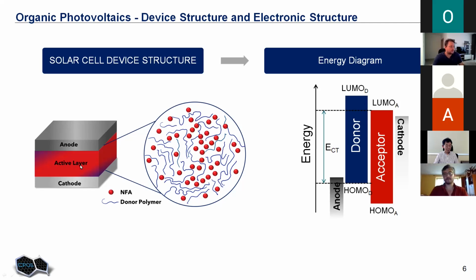Usually it is considered as intrinsic semiconductor, so not doped, sandwiched between two electrodes, cathode and anode. So once we have free charge carriers, which are separated at the interface between donor and acceptor material, free electron and hole can move along the networks of donor and acceptor materials towards respective electrodes. And this is driven by internal electric field because we have different work functions of this cathode and anode. Under equilibrium conditions, there is some uniform electric field and linear band bending inside the active layer. So that is the driving force for separation of these charge carriers. So they will contribute to photocurrent.